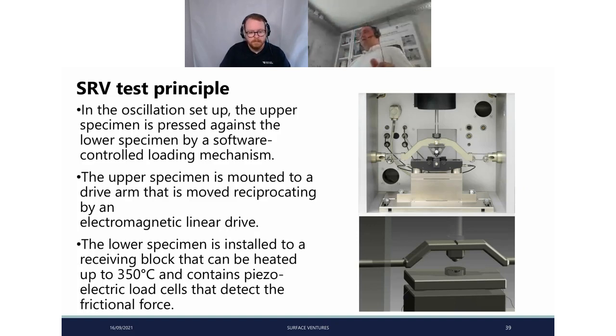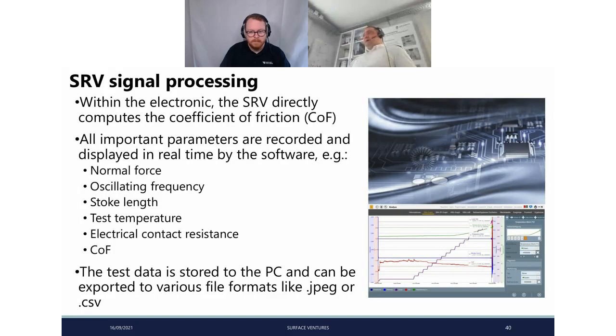You can vary the temperature in the contact from -45 up to 1000 degrees centigrade, which gives you a wide range to cover with your applications and tests. And we have online signal processing within our electronics, so that you can always make sure that the signals are timely synchronous. If you want to understand effects, you have to be sure that, for example, the displacement signal and the friction force signal come in the same microsecond. If you have a time offset in between, then you can't really interpret the results, because you can't correlate them. And then of course, you can export all the data to other file systems, which allows you to import your generated data directly into calculation software for your further simulations and so on.